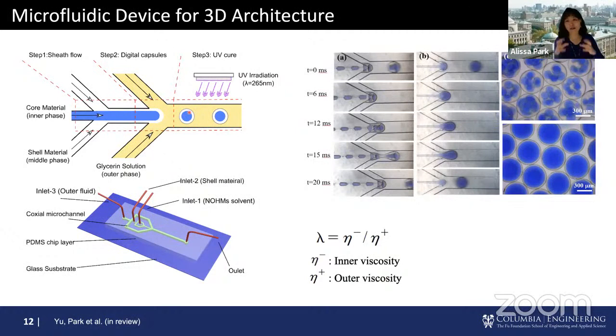You can see that we can make single core, multi-core of a lot of these materials shown on the right. And we intentionally made these particles not a nanoscale, because you can't really deal with nanoscale particles easily in reactor systems. But we were making the 300, 400, 500 micron size much easier to design these particle systems for either duct injection or fluidized bed reactors, or even fixed bed, depending on the applications.